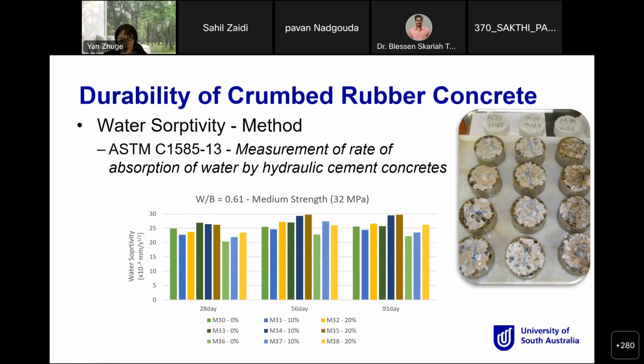shows a slightly lower water sorptivity at all ages. So that's a very interesting result. However, for mix M32, where you see 20% crumb rubber, they did show a lower water sorptivity at 28 days, but it was higher at 56 and 91 days. You see this M32, this yellow color, is lower initially at 28 days, but it will be a little bit higher for 56 and 91 days.